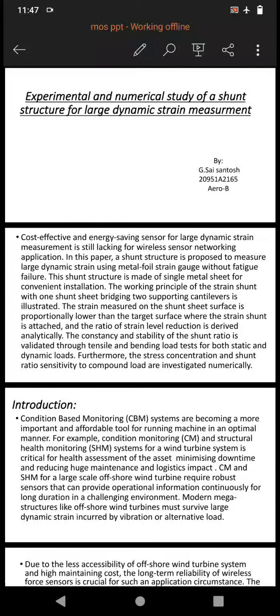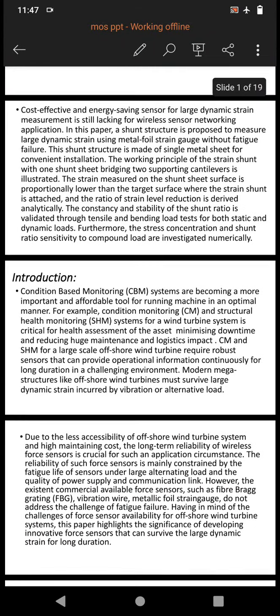The strain measured on the shunt sheet surface is proportionally lower than the target surface where the strain shunt is attached, and the ratio of strain level reduction is derived analytically. The constancy and stability of the shunt ratio is validated through tensile and bending load tests for both static and dynamic loads. Furthermore, the stress concentration and the shunt ratio sensitivity of compound load are investigated numerically.